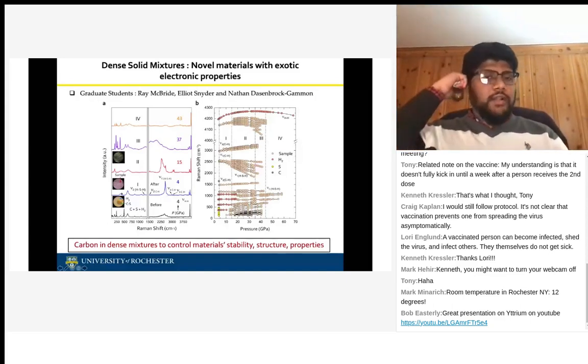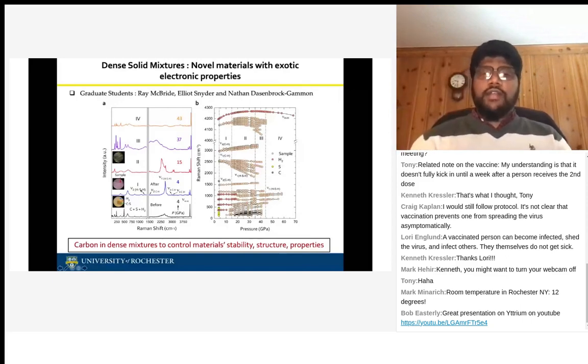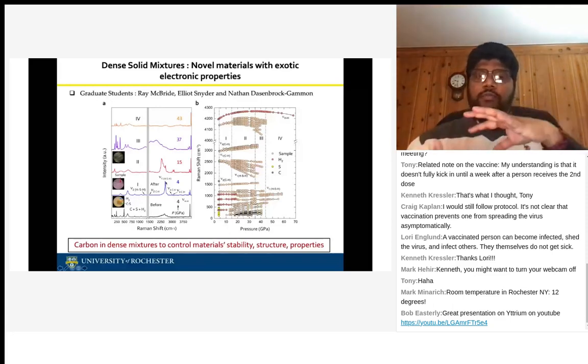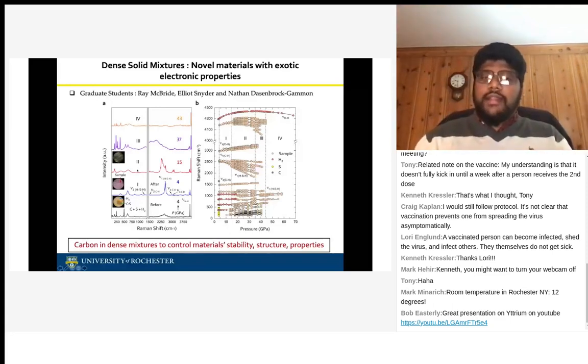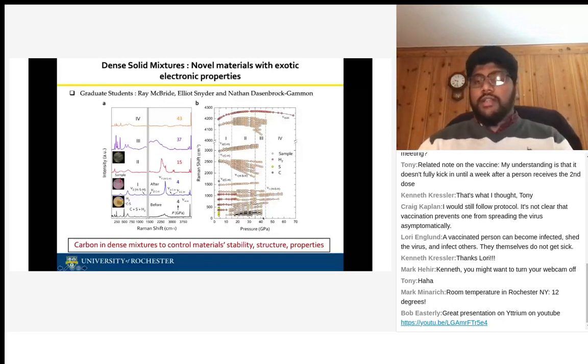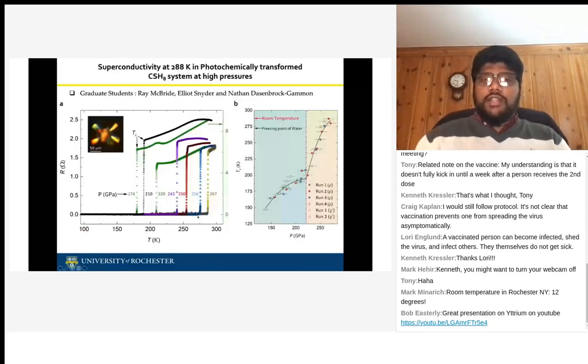So indicating that you engineered a new material which has a different chemical composition and different environment. So when you squeeze this one to really high pressures, you modify the crystal structure in such a way that you can have a favorable superconducting transition. So when you squeeze all the way to 267 gigapascal, that's where we start to see the drop